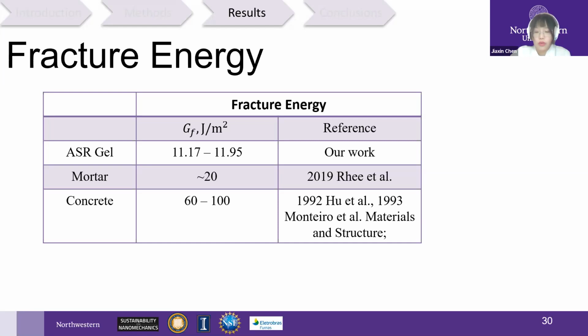Compared with mortar, which is around 20, and concrete, around 60 to 100, our measurements suggest that the fracture energy of alkali-silica gel is an order of magnitude smaller than that of concrete and 2 times smaller than that of mortar generally. More measurements are needed on a larger amount of fragments. We have illustrated a powerful method to measure the fracture properties of alkali-silica gel crystal from the nanometer up to the micrometer length scale.